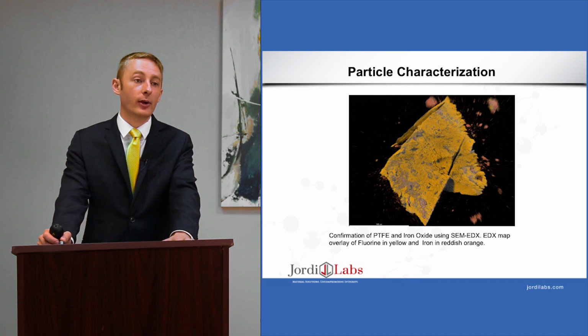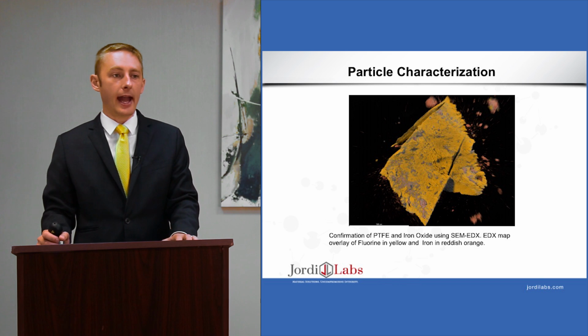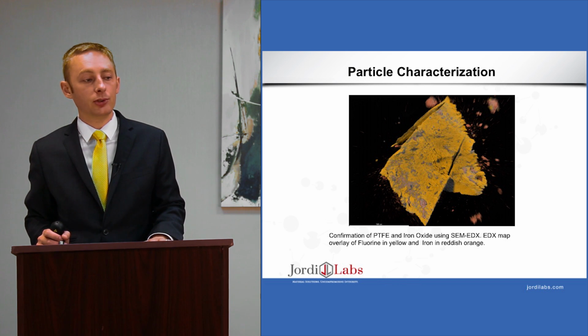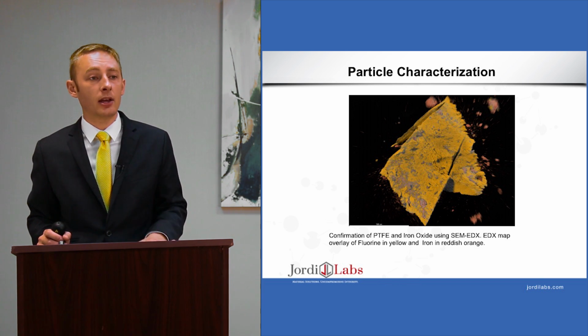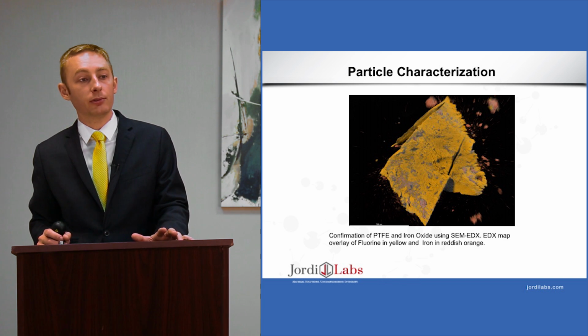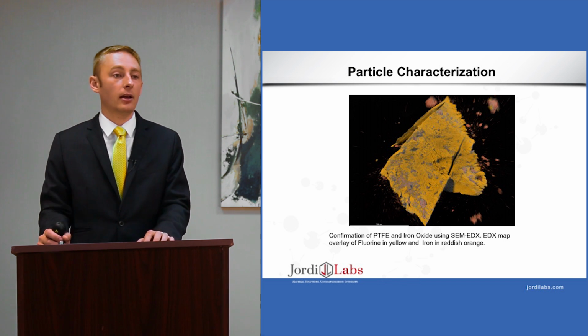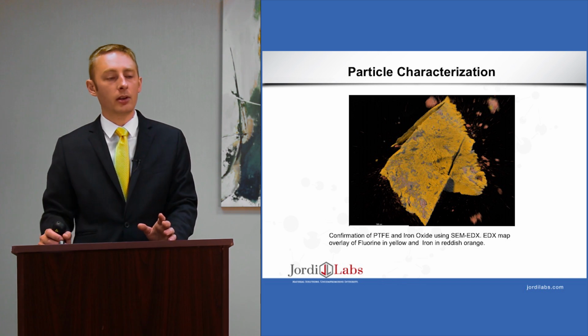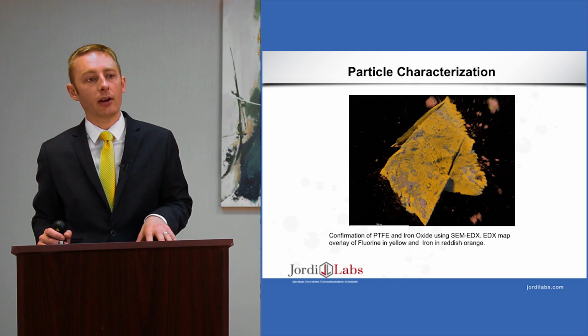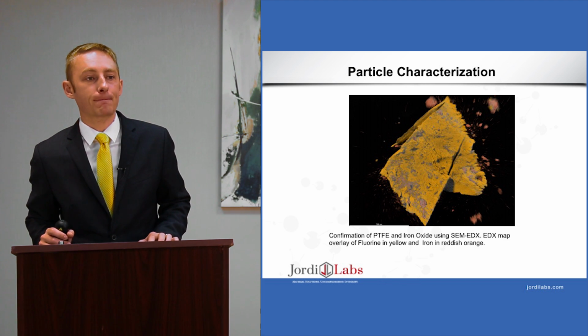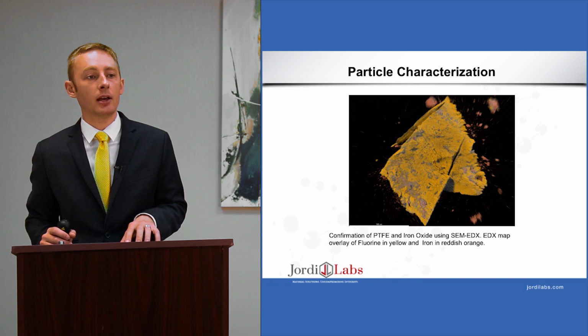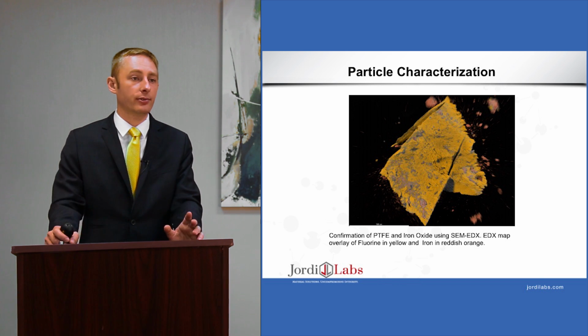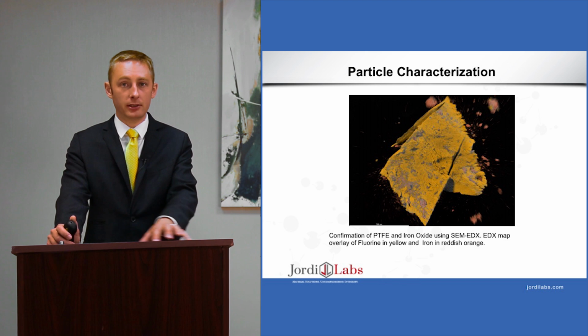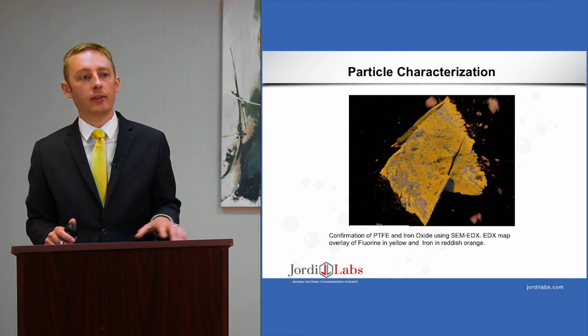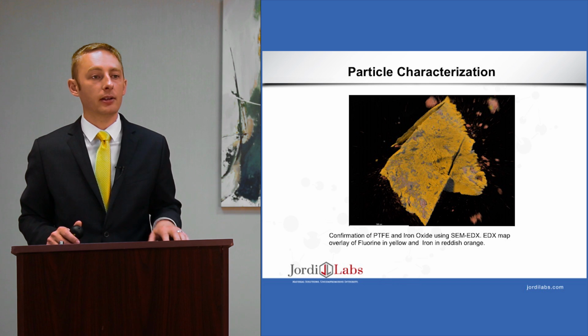SEM-EDX is a great technique for elemental composition, and you can do surface mapping with SEM-EDX. And what we've done in this case is we've confirmed the presence of PTFE and iron oxide using SEM-EDX. And so on the EDX map that you're looking at right now, the overlay of fluorine is in yellow, and iron, that's Fe, is kind of a reddish orange. And so there's a ton of fluorine present, which would be expected for PTFE. And there's traces of iron as a reddish orange.